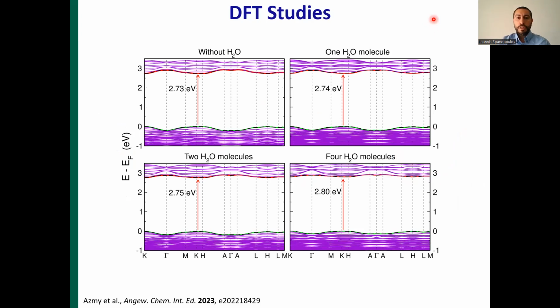DFT studies shed light on the semiconducting properties of the material. This compound is a direct bandgap semiconductor. This is the band structure without any water molecules, and we added 1 water molecule per organic ligand per unit cell, and this is 4 water molecules per 4 organic ligands. This means in that case there is 100% water loading, and you can see that there is a minuscule difference in the optical bandgap for full water loading. This is a great demonstration proving that the water inclusion does not affect the optical properties.